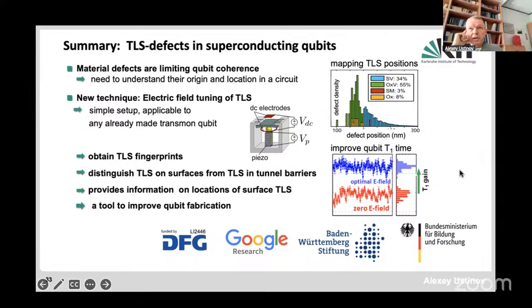The stray junction is the very large area Josephson junction, which is typically fabricated during the process of the standard tilted angle evaporation. So you need to make the top electrode of aluminum, and then you need to come to the bottom electrode using the same type of process. And then the simplest is to make a very large area junction, which you normally consider superconducting. So this is called stray junction. Nowadays, people actually add an additional step in fabrication. They fabricate a bandage to avoid stray junction, which significantly increases the coherence of superconducting qubits.